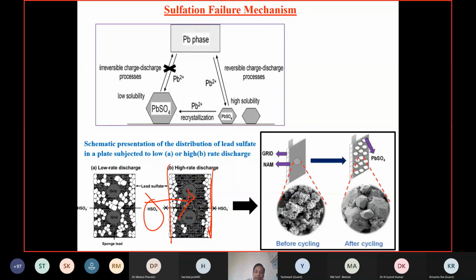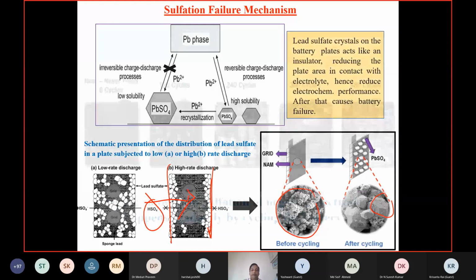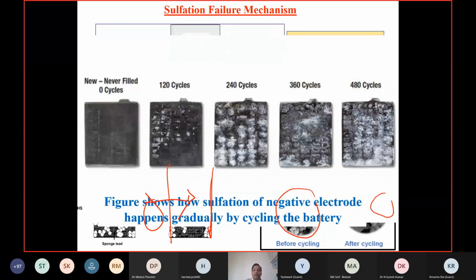Before cycling, they are all nanomaterial, and after cycling, you see big crystals of lead sulfate have formed. This has been analyzed by XRD, SEM, and other techniques as well. So this is the main failure of a lead acid battery. That's how you see the difference. You can easily understand when you cut open the cells. This even I have seen in the industry. This is the major problem of the lead acid battery.